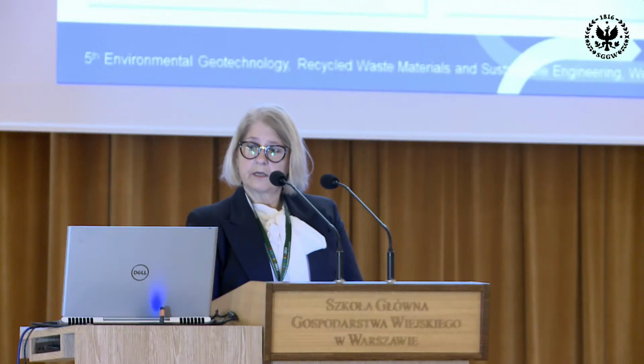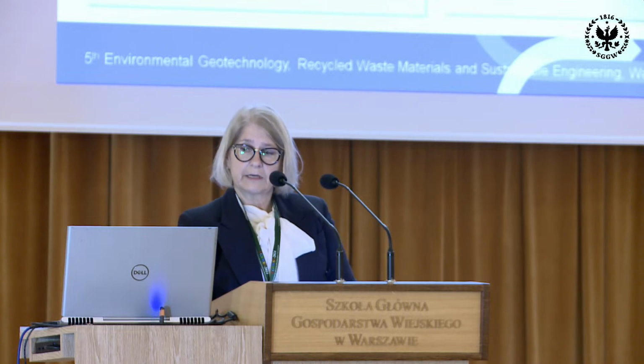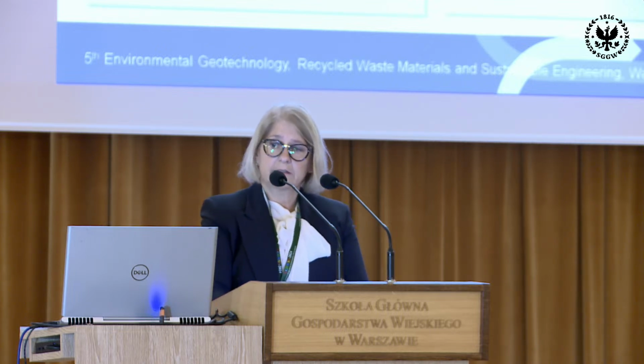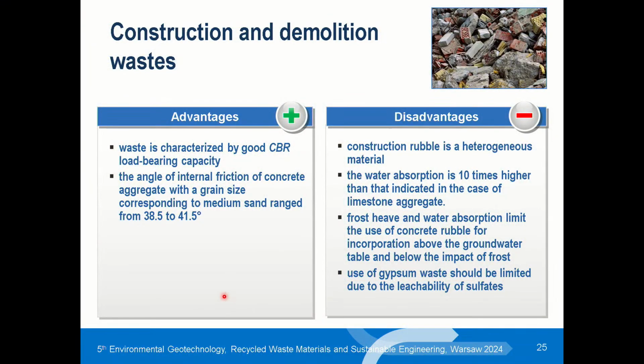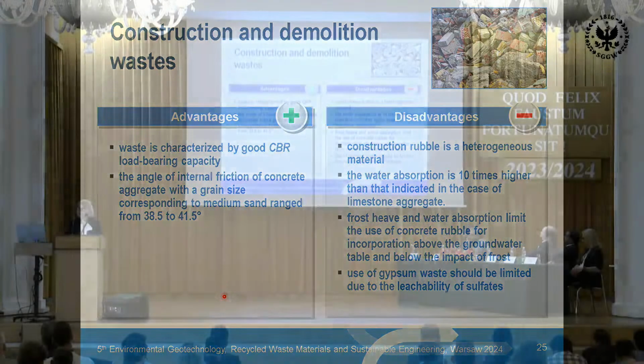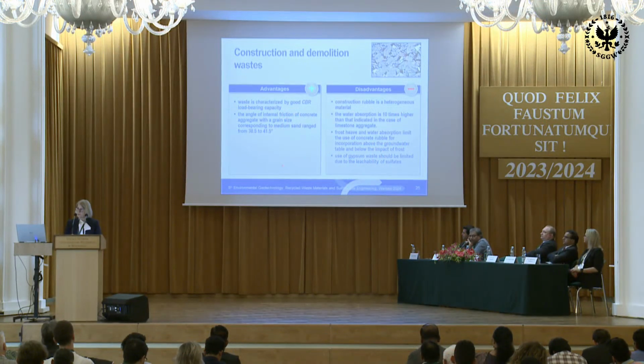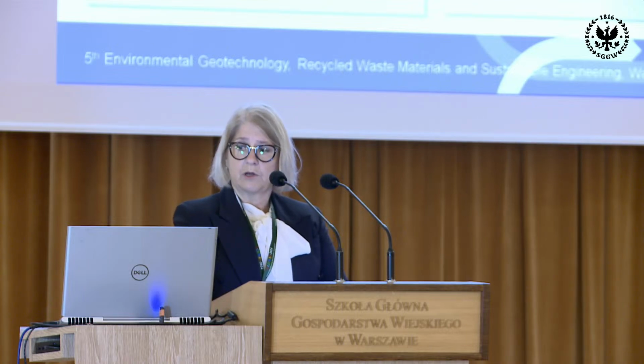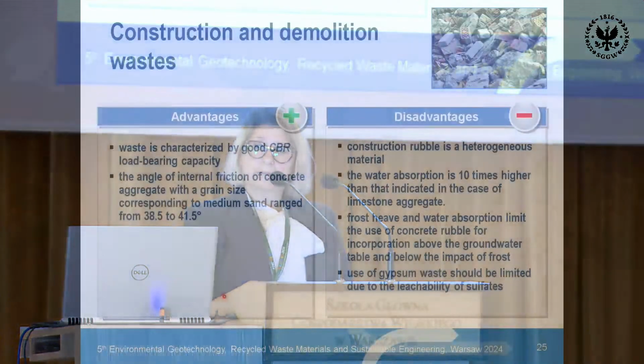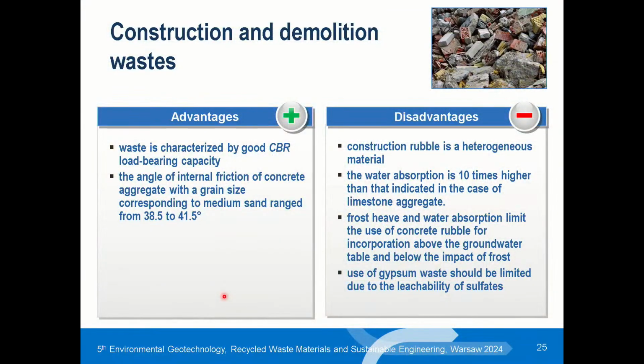Advantages are very good CBR load-bearing capacity and great angle of internal friction. Disadvantages is that it's a heterogeneous material. Water absorption is 10 times higher than indicated in the case of limestone aggregate. Frost heave and water absorption limit the use of concrete rubble for incorporation above the groundwater table and below the impact of frost, and use of gypsum waste should be limited too.